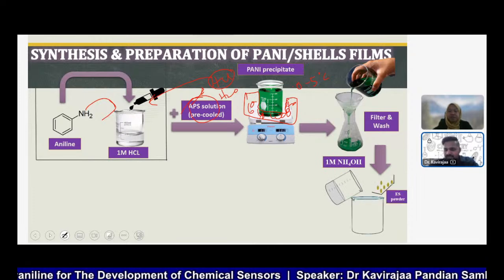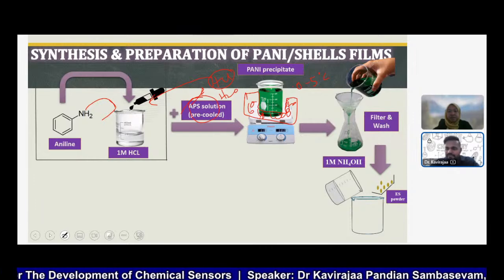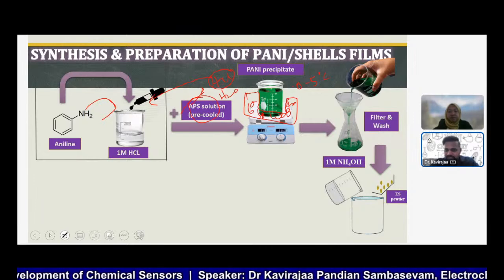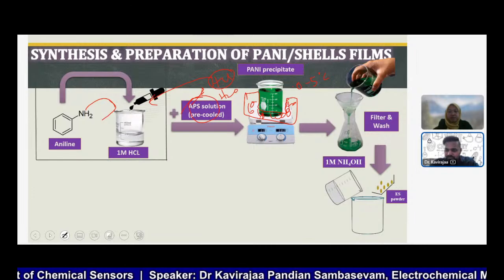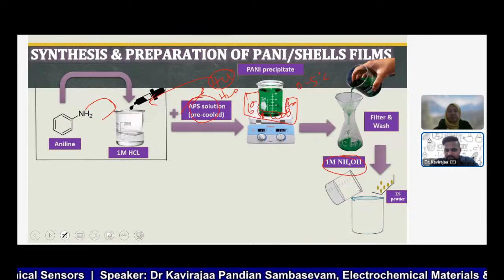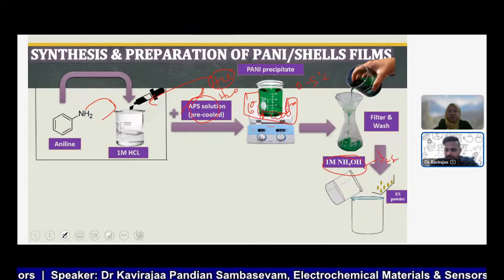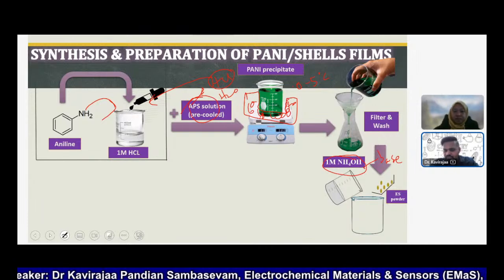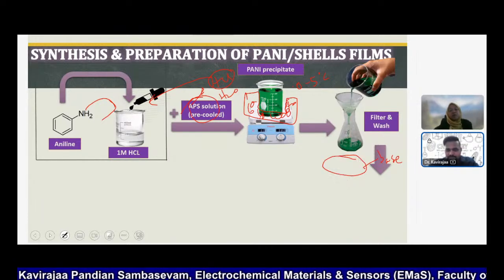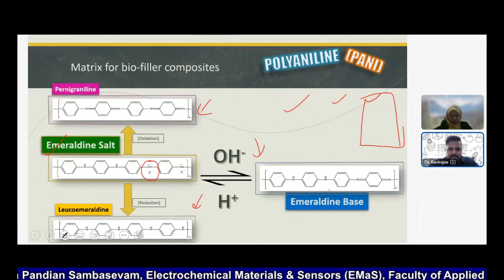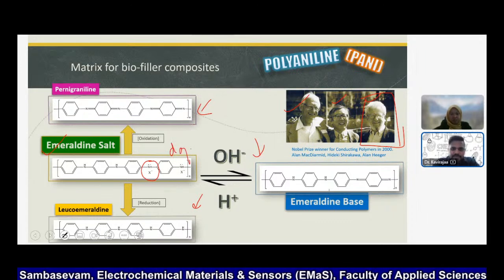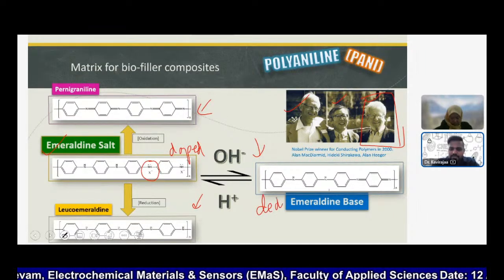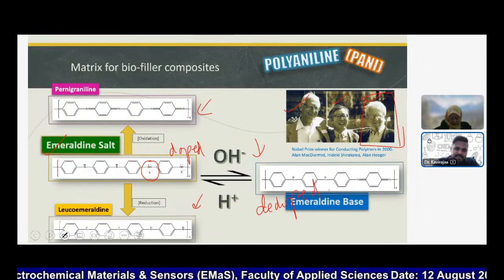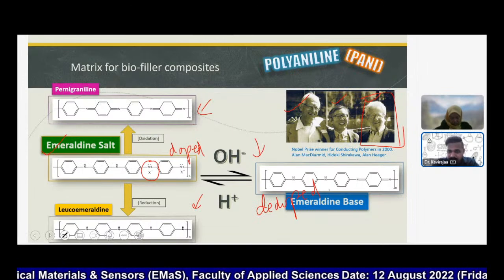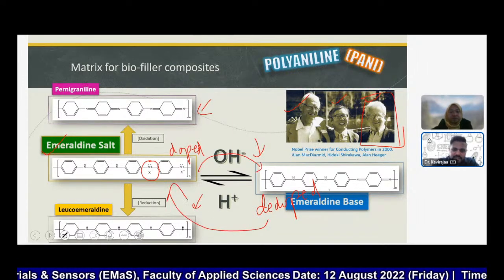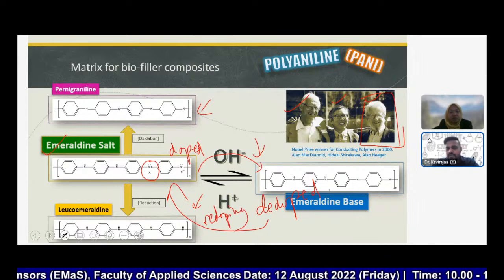And then, after we filter and wash it, we will collect the precipitate. Once we collect the precipitate, we let it immerse inside the ammonium hydroxide. Ammonium hydroxide is a base. The reason we are using ammonium hydroxide here is to dedope. Dedope means something like, I have to go back here. Okay, all right. So this is the doped state. This is the de-doped state. Initially we get the doped state, but then we go back to the de-doped state, and then we will do a re-doping.